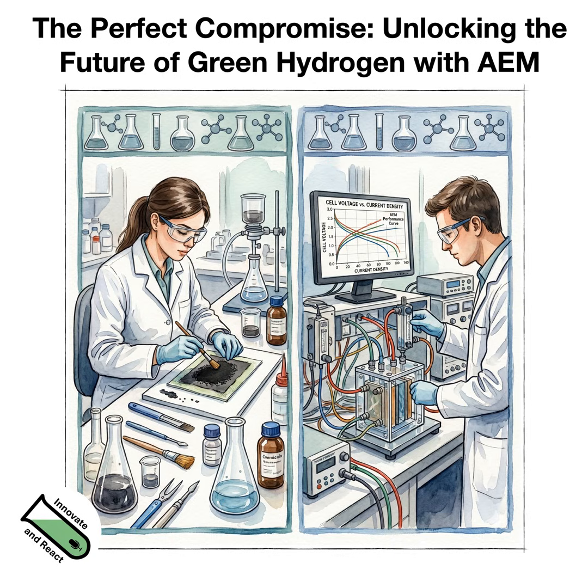And nickel-sulfur is able to undergo oxidation and therefore increase hydroxide layers on the surface. So in this case, it improves the performance for the oxygen evolution reaction and also for the hydrogen evolution reaction due to the several advantages of nickel-sulfur. Interesting. So you can use the same material for both electrodes. Yeah, exactly. We varied the parameter during the electrodeposition process.